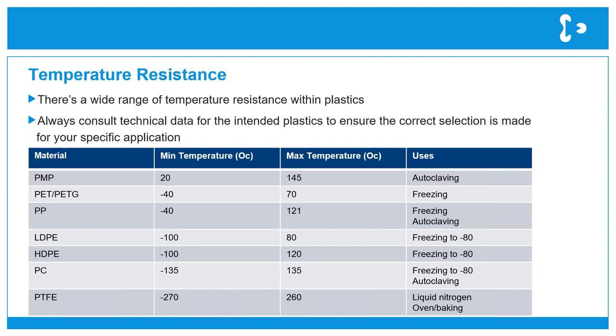There are a lot of user applications and processes that have specific temperature requirements. Many applications often require freezing or heating of samples, either for storage or processing aspects of certain experiments. So again, always consult technical data for minimum and maximum resistance of polymers. An example here is PETG, where you can see a minimum brittle temperature of minus 40 and a maximum temperature of 70. So this container can be frozen. If you need low temperature storage at minus 80, then you will be looking at other materials such as LDPE or HDPE and